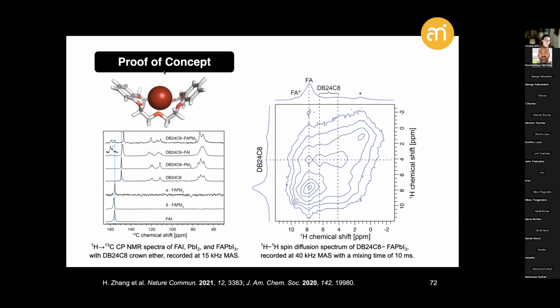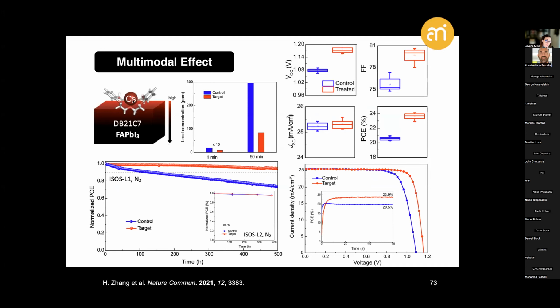Now, in this case, the capacity of this system to competitively bind both metal and A cations enables it to be used as a molecular vehicle or a shuttle to deliver specific cations, in this case cesium cations, within the hybrid perovskite architecture, especially those of the formamidinium lead iodide-based perovskites that, as you might remember from the earlier part of this talk, are not very easily thermodynamically accessible at ambient temperatures, but which can be stabilized through, in this case, a gradient of cesium cations that is leading to the further stabilization and improvements in the resulting performances